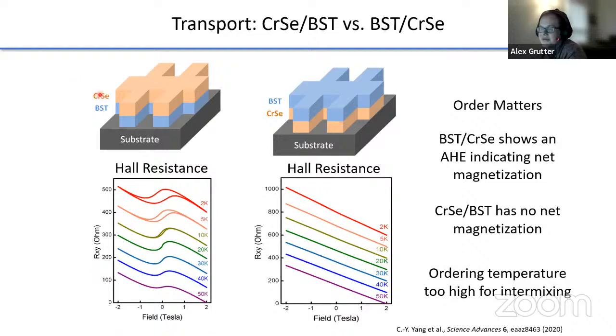So one might imagine worrying that the chromium diffuses into the bismuth antimony telluride and what you end up with is effectively a doped topological insulator again. But if that were true, we would expect that to appear to a certain degree regardless of which order you grow the layers in. And so this doesn't seem like an intermixing type effect, and it's a much better candidate for magnetic proximity.